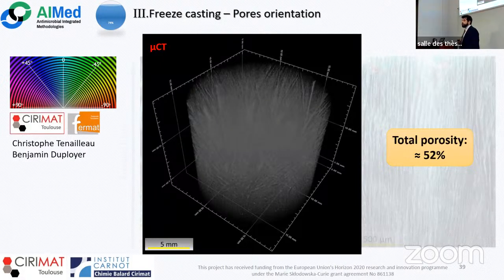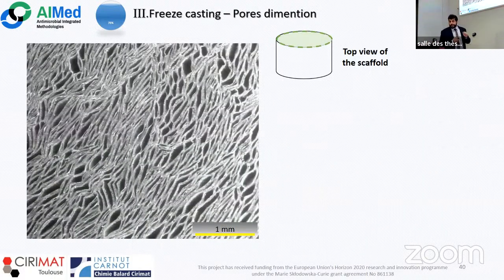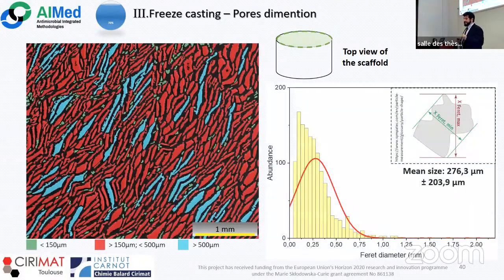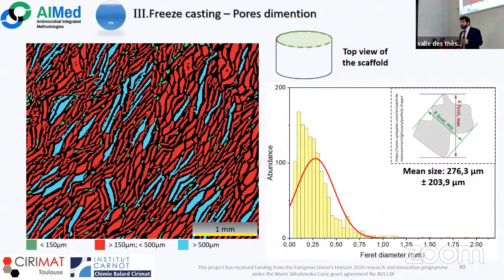This kind of orientation has also been corroborated by micro-CT analysis performed with the Fédération Fermat, in which, by doing a region of interest characterization, we were also able to estimate the total porosity of the scaffold, which was 52%. Then we wanted to study the pore size, and to study that, we worked on the top view of the scaffold. In this case, we were able to observe that most of our pores had a diameter of more than 150 microns, which is the size usually defined as suitable for cell colonization.